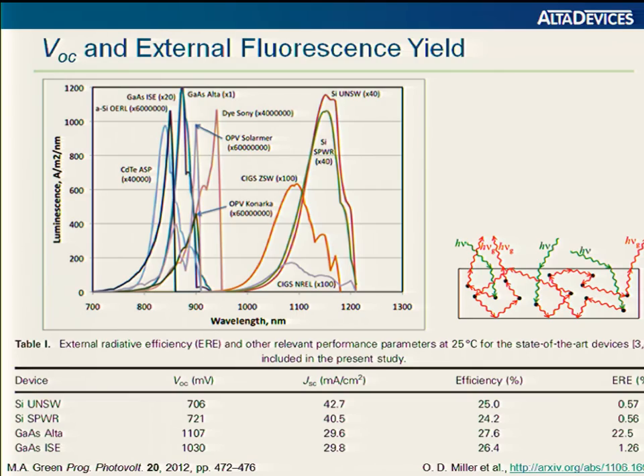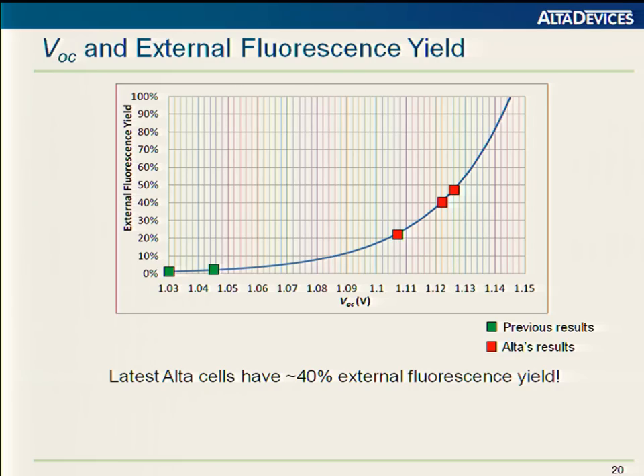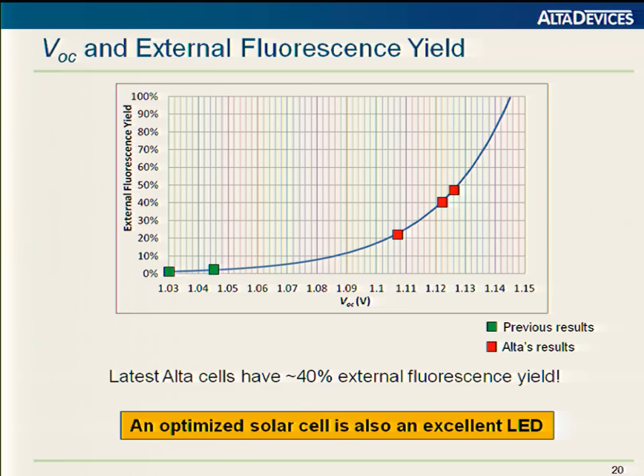So this, again, is another measure of the efficiency of external photon emission at open circuit. I can use the same methodology, assuming the external quantum efficiency is independent of the cell, and look at these different gallium arsenide solar cells. I can then graph external fluorescence yield as a function of VOC. And we believe with our latest results, we're getting above 40% external fluorescence yield, which even in the LED community is a respectable number.